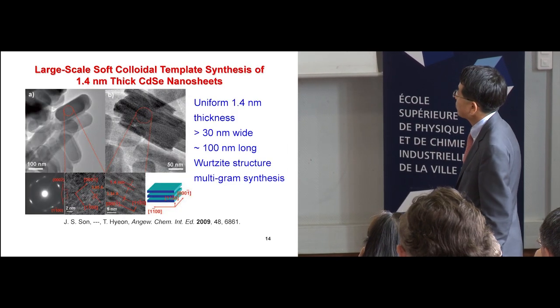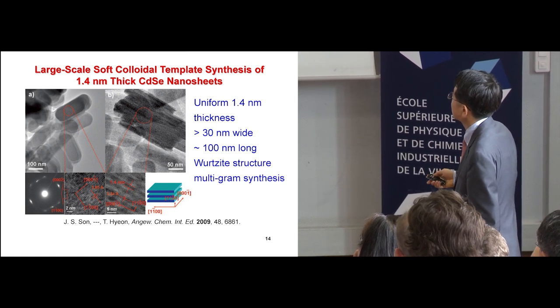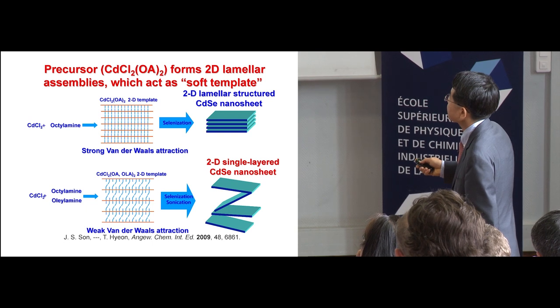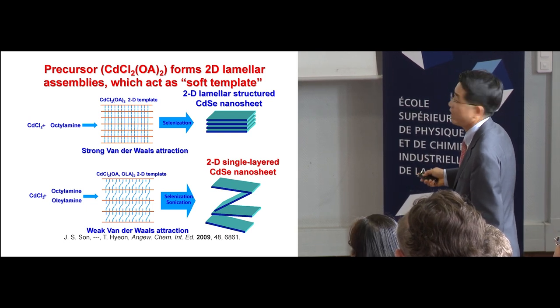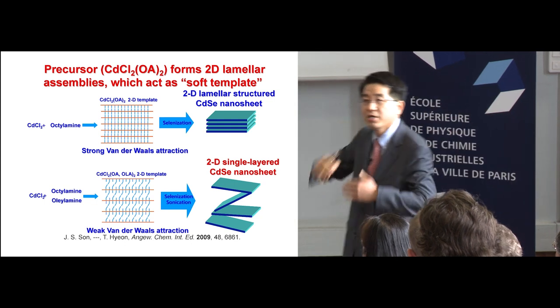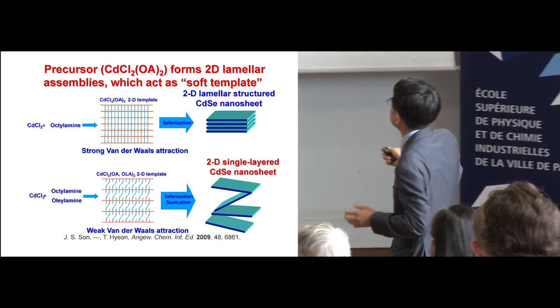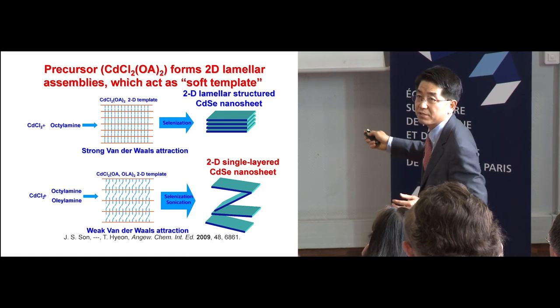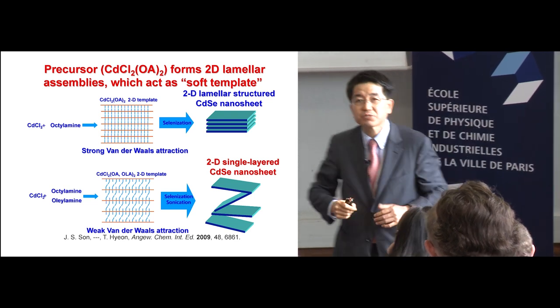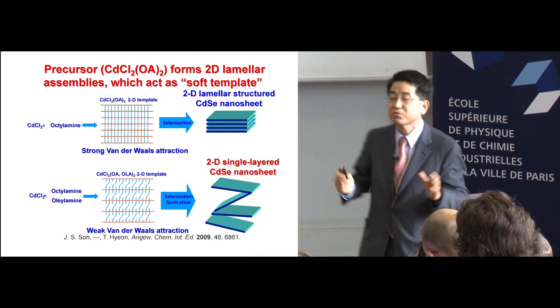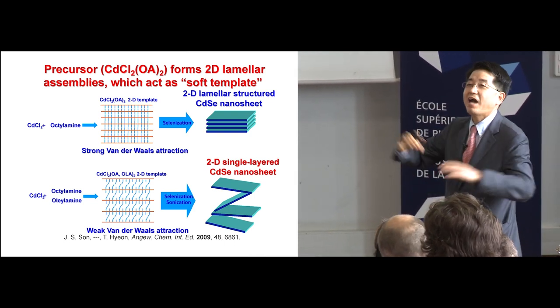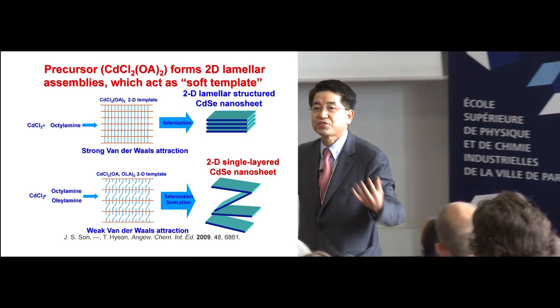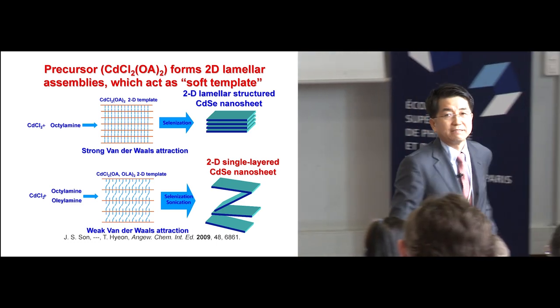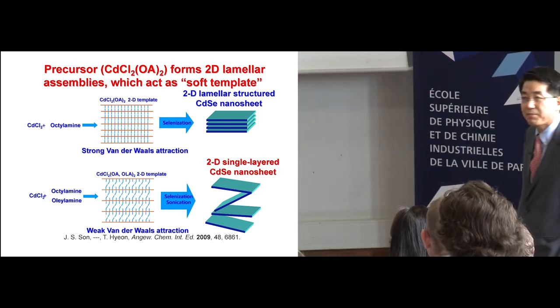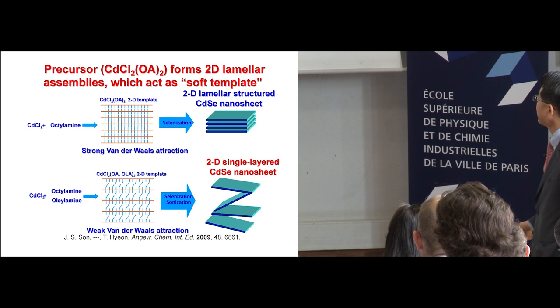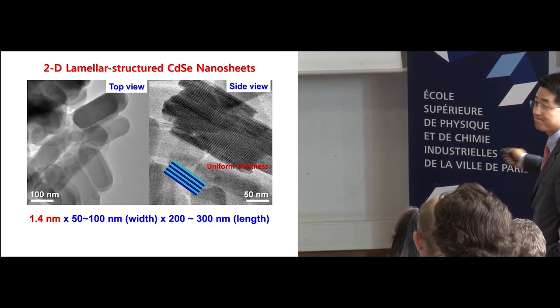And later, we also modified this synthetic process, mixing octylamine with oleylamine. We can decrease the interaction between the layers, okay? Starting with CdCl2, it forms this kind of structure, it has been known. And by decreasing the interactions between these layers, we could make exfoliated, separated, single-layered nanoplate structures, okay? Obviously, quantum size. The thickness didn't change. It's still 1.4 nanometer. So this is basically stacked, okay?